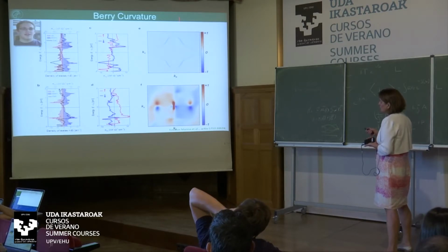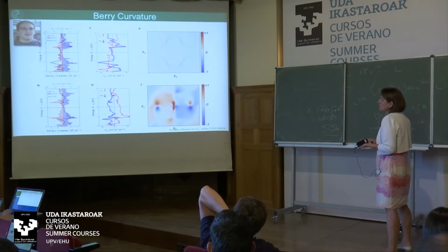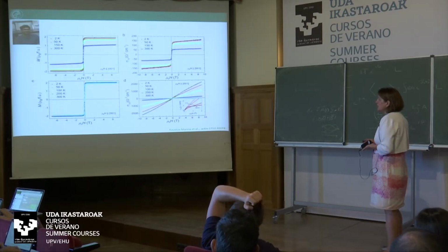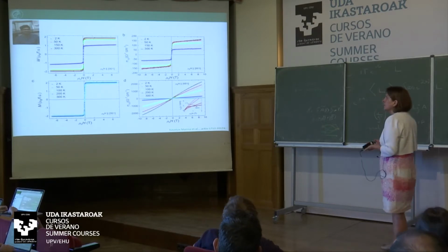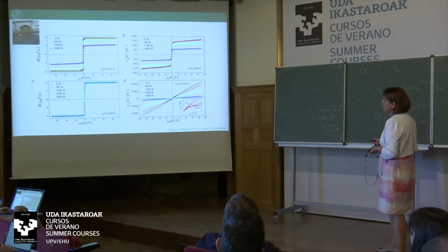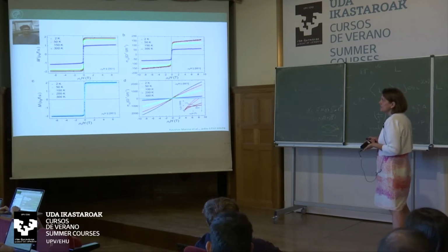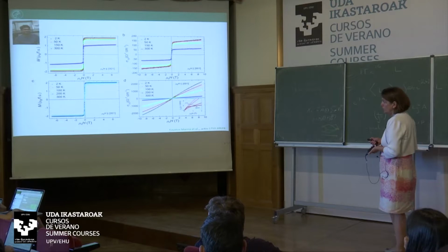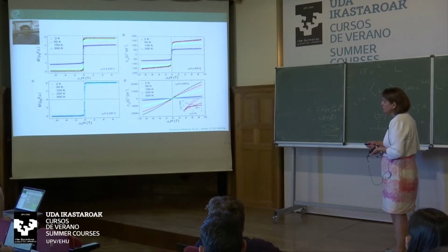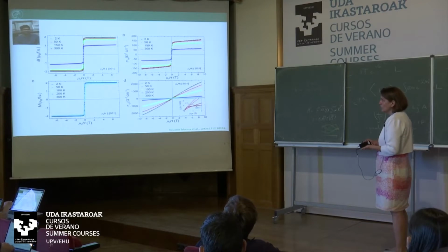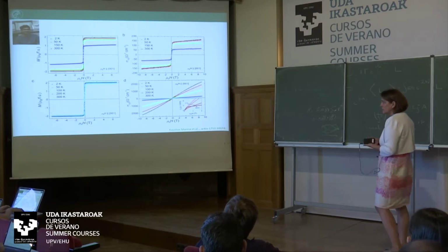But if we remove the mirror plane, they can cancel, and the Berry curvature, the Anomalous Hall effect, becomes 0. And this is interesting because this is what we like to do then: to prove that this has nothing to do with the magnetization, we made a compound which has 26 valence electrons. So from the electron counting rule, we know it should have 2 μ-Bohr. So you see here is the magnetization curve, 2 μ-Bohr per formula unit. And we made another compound which also has 2 μ-Bohr and has no mirror plane. So it has no inversion symmetry.